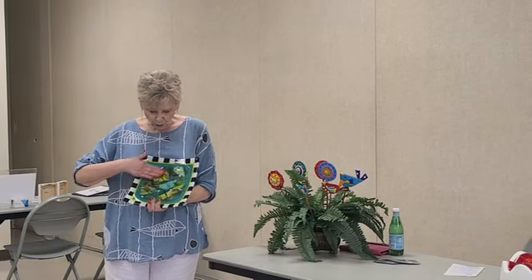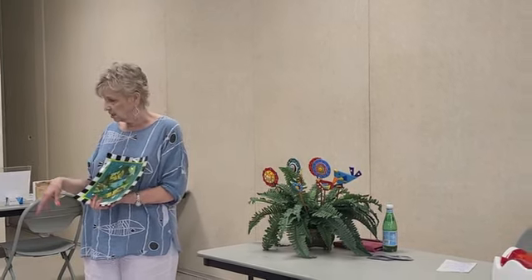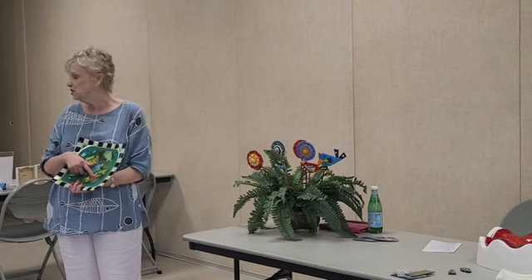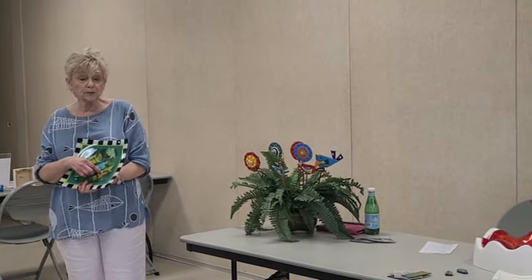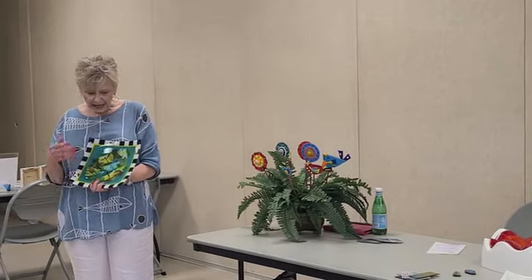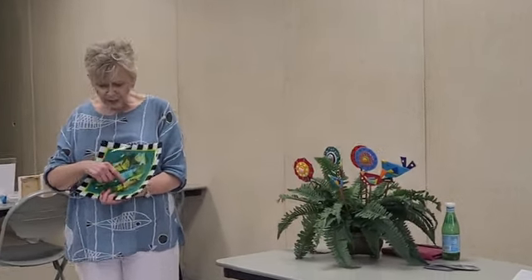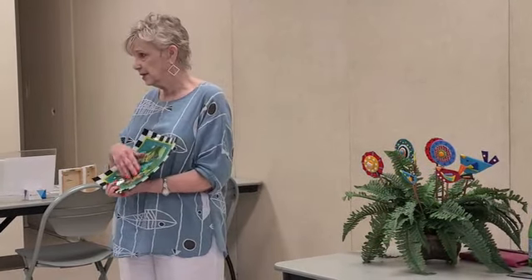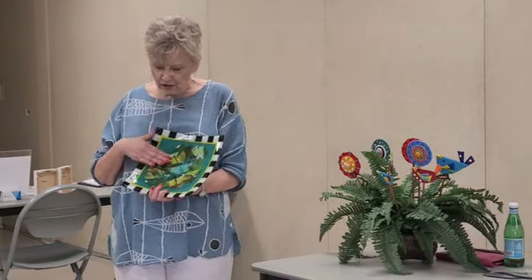And this required us to think about cool colors, hot colors, stacking colors so that we could get these brown places in here. She didn't put brown in there. That's the chemical reaction between some of the colors. So you have to know things about the colors of your glass and how they behave when they're together. If she hadn't put the yellow green right there by her other green, it probably would not have turned to that brown color, or put the powder on it. There are different grades of glass powders and things called frit that are little broken up pieces of glass. And so you do have to know something about the chemistry of the glass.